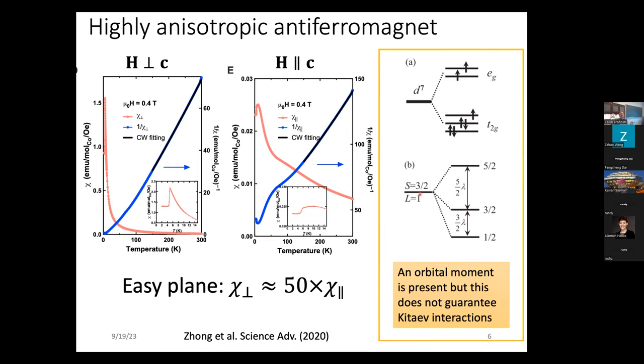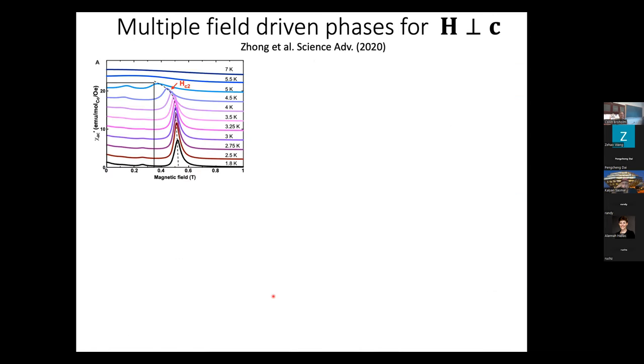And since from spin one and spin 3/2, I can form spin half, spin 3/2, and spin 5/2, I end up with a spin half spin orbital angular momentum ground state. And so this is now going to be a spin degree of freedom that, as you rearrange the spin, you're also changing the charge distribution on the ion. And so we're going to expect that there will be anisotropies associated with that. And it's reflected, as we've just mentioned, in the very strongly easy plane anisotropy of the system.